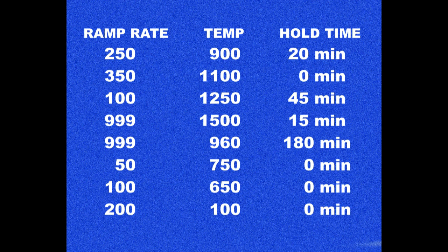Then we can go as fast as possible, which is 999 on my kiln, up to 1500 degrees, which is full fuse on my kiln, and hold it for 15 minutes, and this is where the dams are needed so the glass doesn't spread out and thin on us.